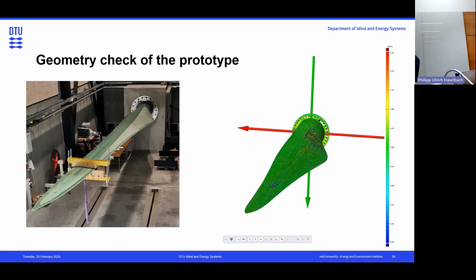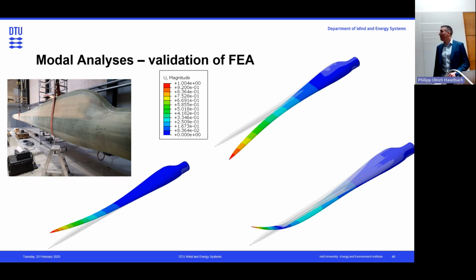Then after we have manufactured our blade, we run a test and scan the entire outer blade geometry. Because again, as we know, we had a CAD design that deviates a little bit due to the mold shape, but also after we have manufactured it, it might deviate a little bit. Then we run a scan of the blade and update our numerical model again so that we can incorporate it and predict the stresses and so on a little bit better. Then running a lot of simulations, looking into modal analysis and hoping that our model predicts it in a good way, which is also giving us a little bit of confidence, when the stiffness and the weight are more or less right, that the model or the modal analysis response should be more or less correct on a global basis.